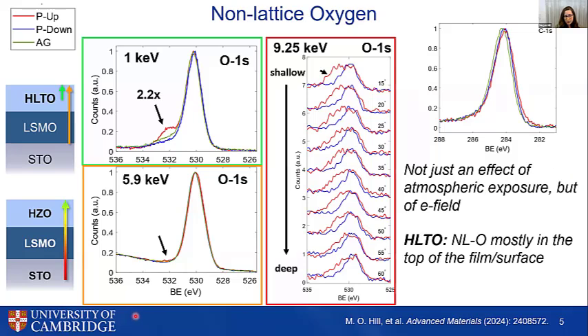But in HLTO, we can see that this peak isn't as obvious at 5.9 keV, suggesting that mostly this non-lattice oxygen occurs at the top of the film. But then looking at the HZO, we can see that as you go deeper, from shallow to deep in this angle-resolved HAXPES measurement, we still see this peak present until we get so deep that we're really probing mostly strontium titanate. So in this case, we have non-lattice oxygen throughout our film.